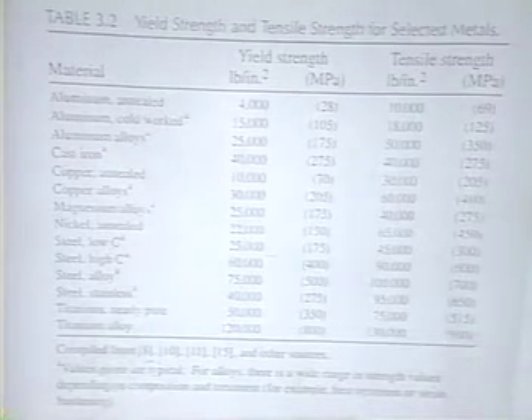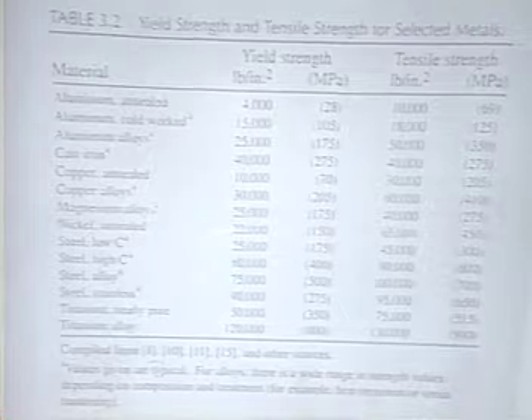Okay, looking at the yield strength and the tensile strength, again, aluminum in the annealed condition has a very, very low yield strength. That means that we can change the shape with a minimum of energy and force, a very, very low 4,000 pounds per square inch stress. And the tensile strength, the limit of uniform deformation, the peak in the stress-strain curve, is 10,000 psi or 69 megapascals.